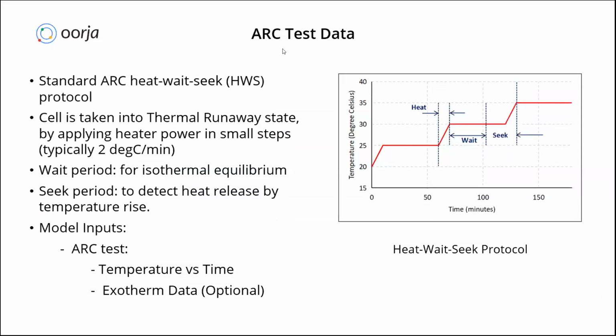So, for example, when we are talking about thermal runaway modeling, we use the ARC test data, wherein we use the standard heat wait seek protocol. If we go for thermal runaway modeling the traditional way, wherein pure physics-based models are used, one needs to know all the side reactions, how those reactions are happening, what coefficients are involved, and what kind of materials are being used inside the cell in order to model the entire thermal runaway phenomena in a cell. But most of the time we do not get access to the internals of the cells itself, and hence modeling thermal runaway initiation is a big challenge with the traditional physics-based modeling way.